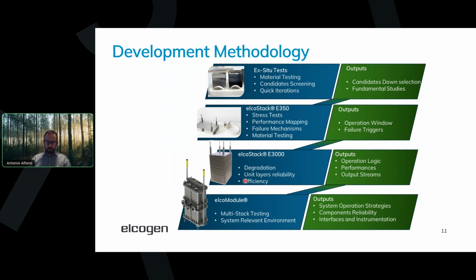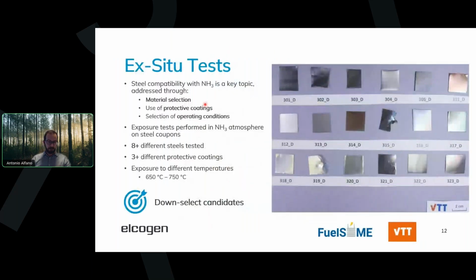We will show a bit of everything in this slide. We have seen already quite a few examples about how coupons of different metals react to ammonia. And what we have also done within this FUELSOME project together with VTT is really studying how those materials react for different temperatures, different operating conditions. Different steels were tested. We also tested protective coatings, 3 of them in different variants of thickness and exposed to different temperatures. And I believe you see something familiar that you have seen in previous slides.